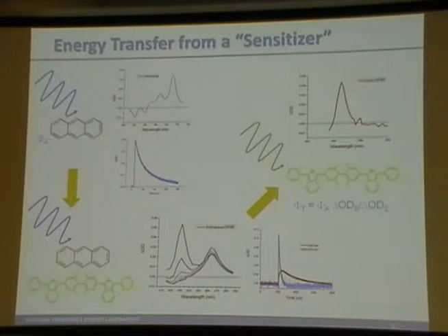The idea is that you excite anthracene just alone in solution. You measure its triplet-to-triplet absorption. Remember, most often you can't measure S0 to T1, it's ground state absorption. But you can measure the spin-allowed transition of T1 to some higher-lying Tn, is just usually what we say. So that's what this absorption is here. So we measure that. We measure the lifetime. It's usually long, 50 to 100 microseconds. Triplets live a long time typically.